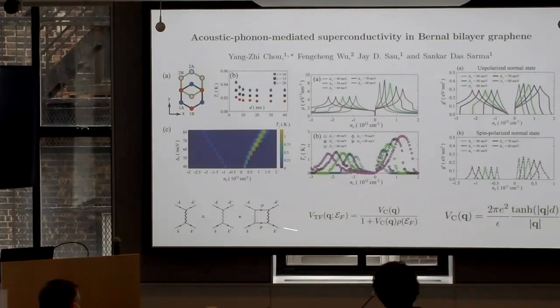We do the same. I'm summarizing the whole result here for you because I was not sure how I'd be doing with time, because there's one other thing I want to talk about. The calculation is very similar to the last one, but there is one difference here because TC is so low. Adding mu star in the last calculation changed our TC from 4 Kelvin to 2 Kelvin. Here, TC being this low, I insisted that we must include the mu star effect, meaning the repulsive interaction effect.